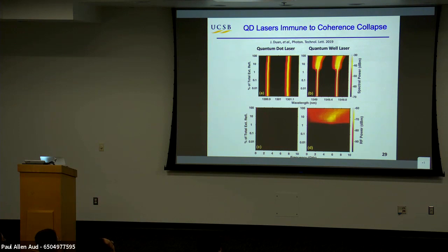If you look at the noise out of the laser, again, noise at low frequencies, 0 to 10 gigahertz, you see nothing up to about 1% reflection, and then this whole laser is incredibly noisy. It's just gone completely unstable. And that's, again, very classic coherence collapse that's well known. If you look at the quantum dot, all the way up to basically 100% reflection, you don't see anything. And if you look at the noise in here, again, you don't see anything up to there. So there's a huge difference between quantum wells and quantum dots, and it's just what you'd expect.